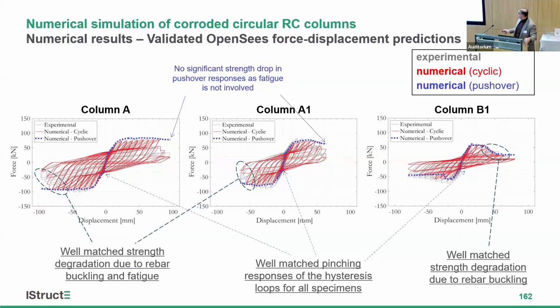But then we did the simulation, and this is the result of the test. So we could simulate this backbone curve. Essentially, we do pushover. Pushover is just a monotonic push to get the capacity, and then also the cyclic. And we could simulate the fatigue and the failure of the column. And we could see this is essentially when the bars buckle. When you have buckling of the vertical bar, they lose strength and increase the stress in the concrete, and the concrete crushes quicker. And that is what we see in the degradation of the column response. And in cyclic loading, we have combined tension with compression. But this kind of model is quite useful, and I'll show you in the next few slides that we can use it for UK problems as well.